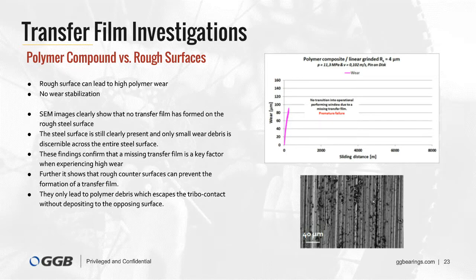To corroborate these statements, scanning electron microscopy was applied as before. What we see here on the right image of the SEM is that we don't have any transfer film. The only thing we can see is polymer-based wear particles not forming a transfer film. This surface is still aggressive in terms of abrasive-induced wear actions. So we can explain the higher wear based on a missing transfer film.